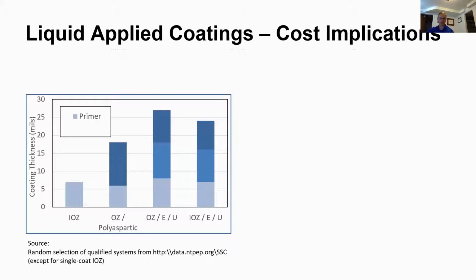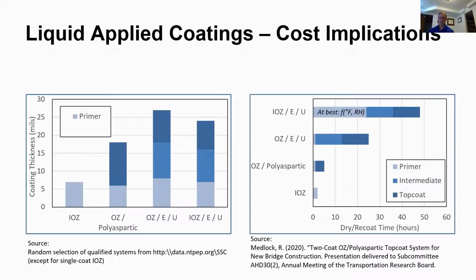This slide is meant to illustrate the difference in coating thicknesses of the major paint systems. The two systems on the right, OZE and U, and then IOZE and U, are the traditional 3-coat paint system. The x-axis here is the overall coating thickness in mils, and you can see that a 3-coat paint system is approximately 25 mils thick. And then over to the right is a single coat of IOZ. You can use a single coat of IOZ as a corrosion protection system. It provides a lot, or actually pretty significant cathodic protection as well. But the thing I want you to understand here is that there are some cost implications.